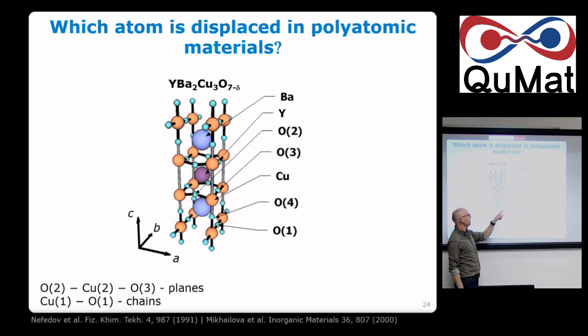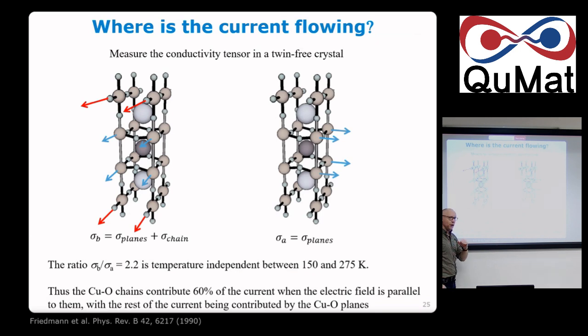Why don't we just electromigrate and try to move that oxygen with electromigration, right? The first thing you have to understand is how the current flows in this material. That was already done. It's an old topic. People realized that if you apply the current in what we call the b-axis crystallographic direction, both planes and chains conduct electricity. If you go in the a direction, the chains are inefficient and only the planes conduct. So people deduced that about 60% of the current goes on the chains, a bit more than half. So we still have enough current on the plane.